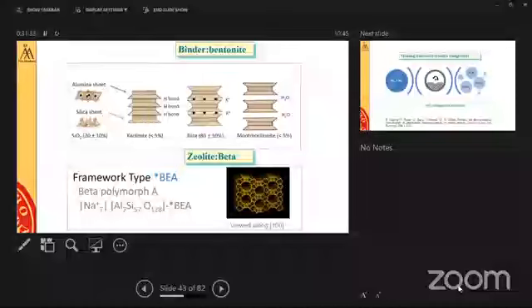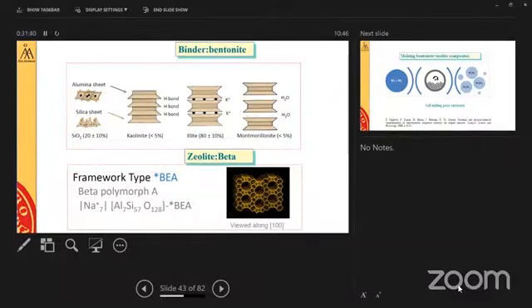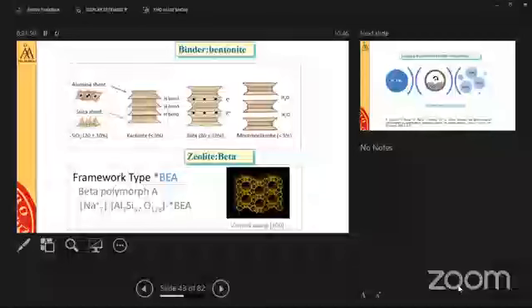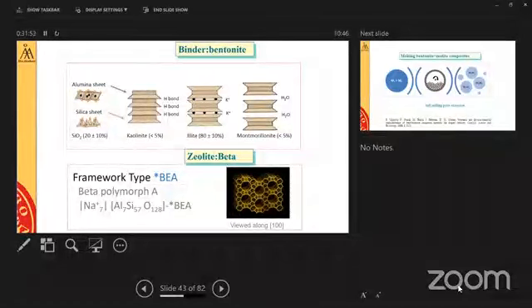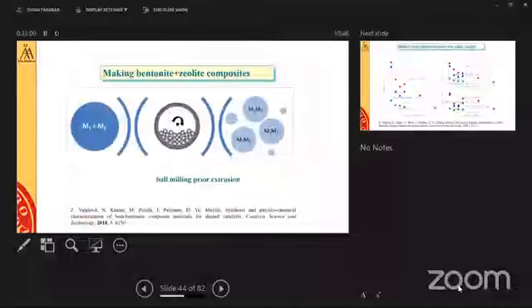one example I want to show is related still to bentonite. Bentonite is relatively complex. It contains different phases: kaolinite, illite, montmorillonite, and then, as I mentioned, it contains also a certain amount of iron. So we started just with mixing bentonite with the zeolite beta. That was just the starting point. So let's see. We mix them together and see what is happening. And we were using a very simple ball milling, even prior to extrusion.